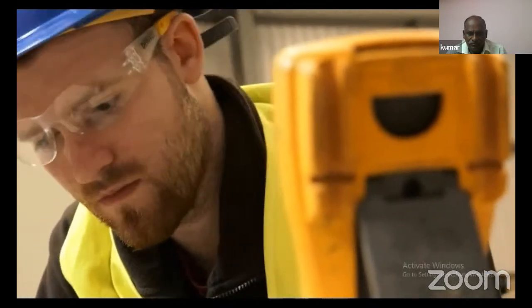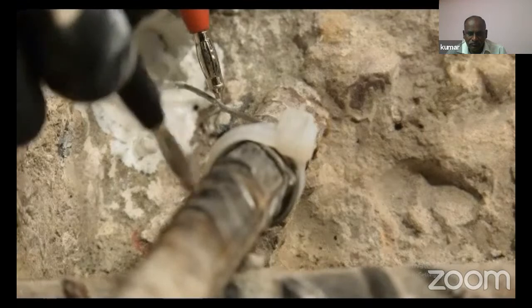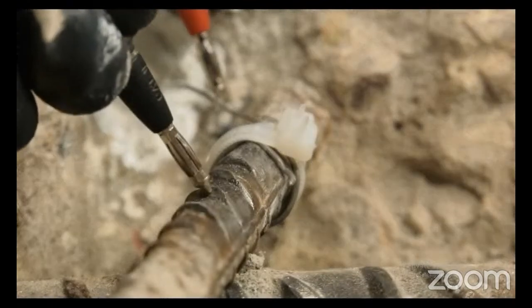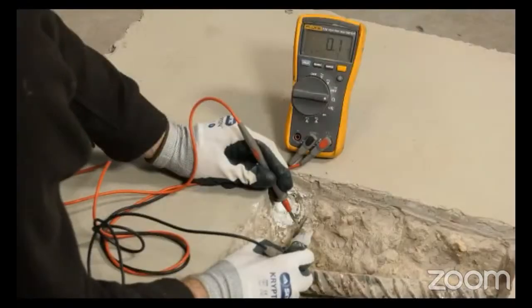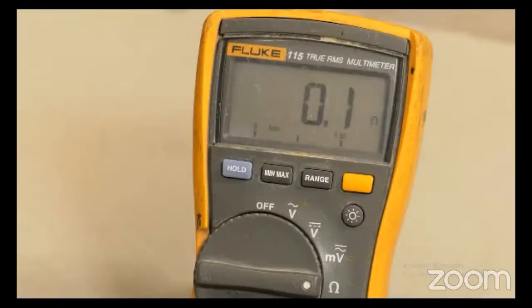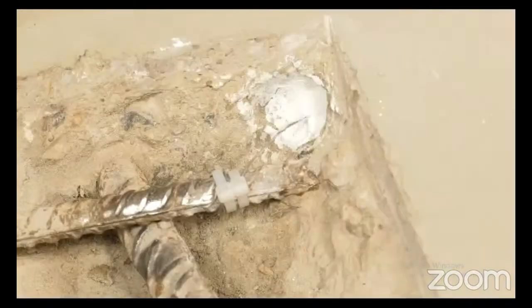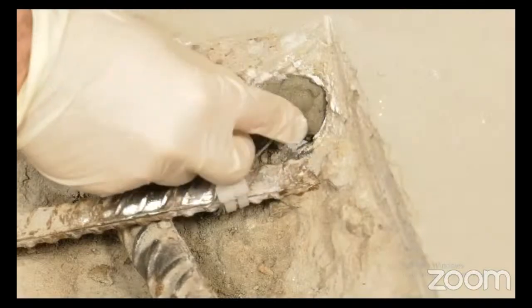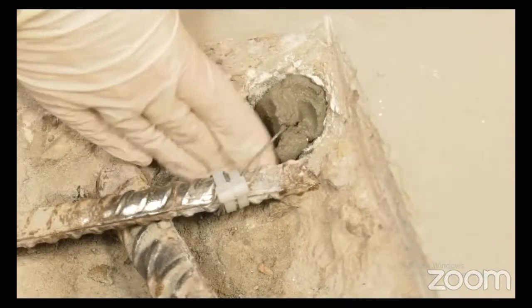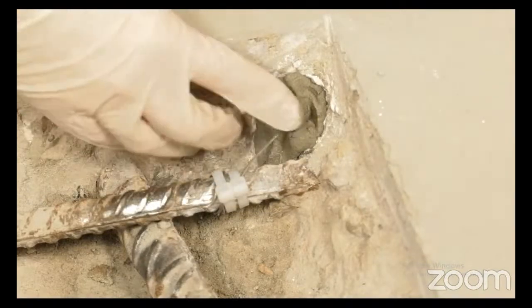If the resistance is more than 1 ohm, then the patch guard anode tying point should be removed. The reinforcing steel should be cleaned and the patch guard anode tying point reinstalled. This process should be continued until a resistance of 1 ohm or less is achieved. If the repair is not to be reinstated within 2 hours, apply a small amount of repair mortar to cap off the anode.